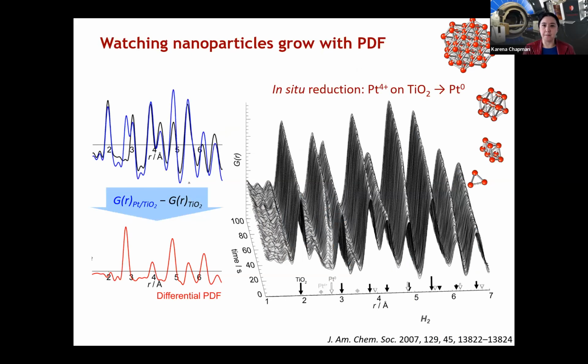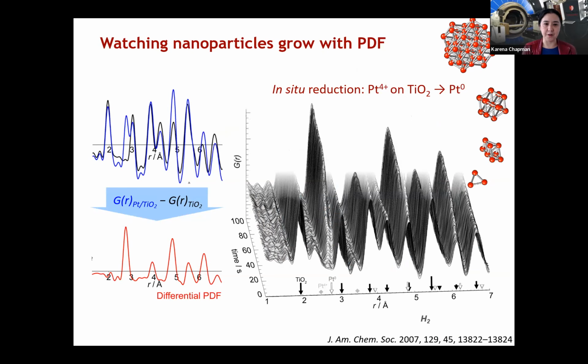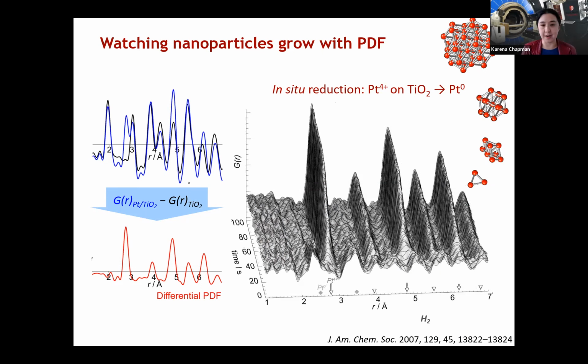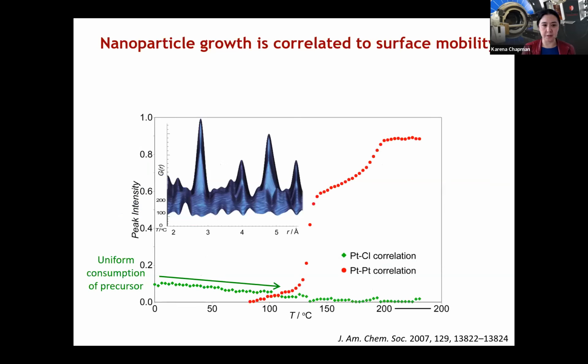This is one of the earliest reactions we were able to watch, looking at nanoparticles forming, supported on a solid oxide support. We initiate the reaction by switching from an inert gas to a reducing gas, which initiates the reduction of platinum 4 to platinum 0, forming nanoparticles on the surface of titanium. Subtracting off the contribution from the titanium support, which doesn't change through the reaction, we see beautiful peaks grow in from the platinum as we're forming it, letting us understand the kinetics and mechanism for this formation. We can quantify the data and pull out peak areas to look at the concentration of different atom-atom correlations.